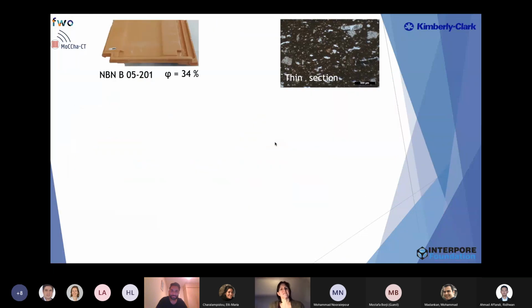An example we tested last year was a roofing tile, where we know that porosity on average is around 34%. Doing in-lab vacuum water intrusion, we can know the normal open porosity of this material. But we also know that this material has a high amount of pores below 1 micron.